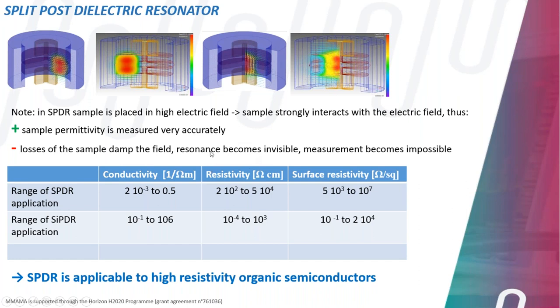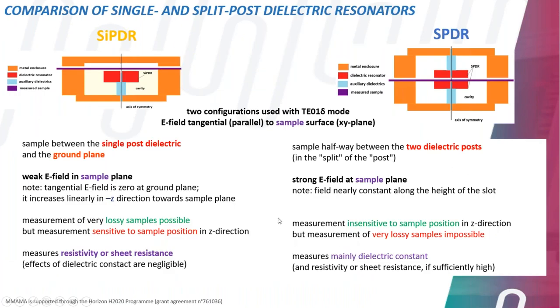This is very convenient for measuring even very low permittivity materials and very low loss materials, but they very strongly interact with the field in the slot. But of course, if we put a too lossy material like a composite, the resonator will be damped. So the whole resonance will go down, will no longer be visible. So this table gives the range of applicability of the split post dielectric resonator. And we conclude that it's applicable to high resistivity materials. For higher conductivity materials, lower resistivity, we have this alternative configuration, a single post.